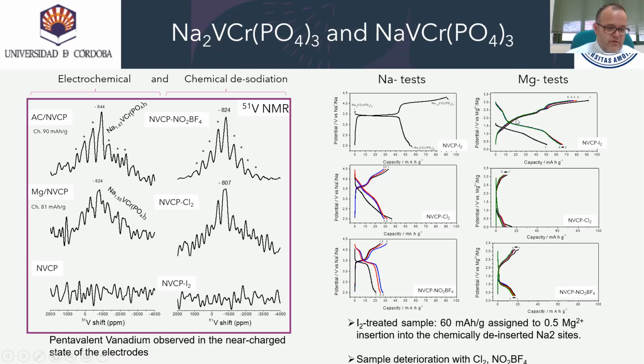On the following chart, we observe that the capacity increases up to 92 mAh per gram, meaning that not only the 0.5 magnesium ions are extracted, but also sodium ions from sodium 2 sites. The poor electrochemical response in sodium and magnesium cells was confirmed when the samples were treated with chloride and NO2BF4, treatment which led previously to electrode deterioration due to the high oxidant power of these materials.